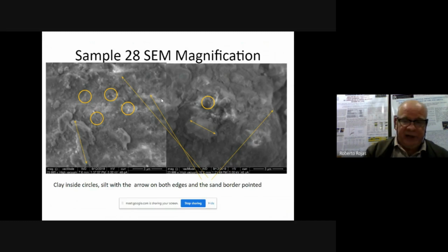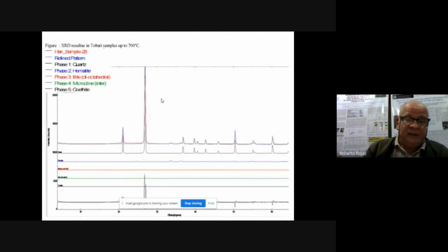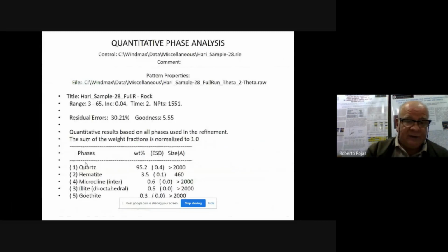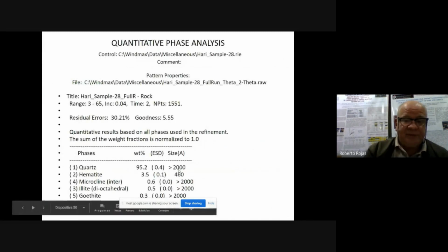So with this, we show our theory. Here are the results of the samples by XRD by the Tulsa University at Oklahoma, the team of Dr. Hari Kumar. We see sample 28 and the phases quartz, hematite, illite, microcline, and goethite. This was seen on the sample. And the quartz here is the size in angstrom. The hematite also has its size in angstrom. Microcline, illite, and goethite. And the percentage in weight, quartz 95%, hematite 3.5%.